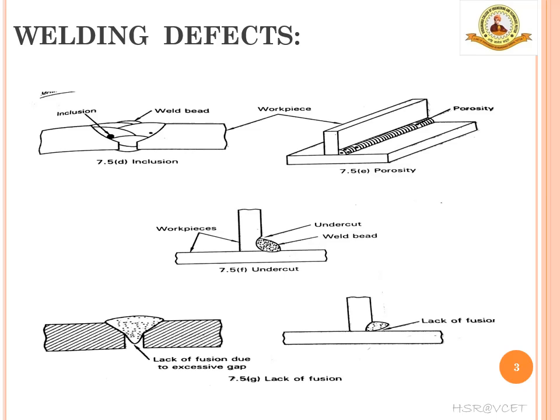Next is porosity. Porosities are small voids or cavities that are formed when gases are trapped in the solidifying weld metal. Porosity can either occur under or over the weld. Causes are atmospheric contamination due to inadequate shielding gas, excessive oxidized workpiece surface, use of wet electrodes, and excessive gas released during welding.